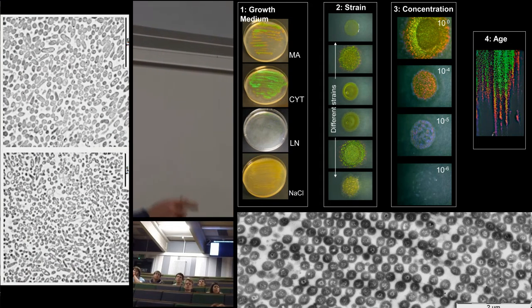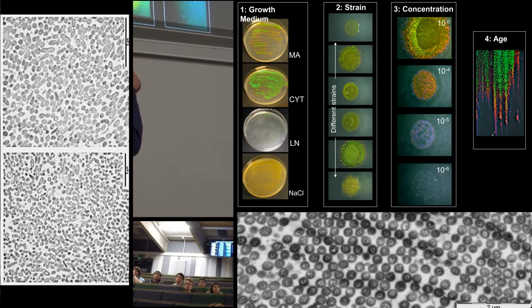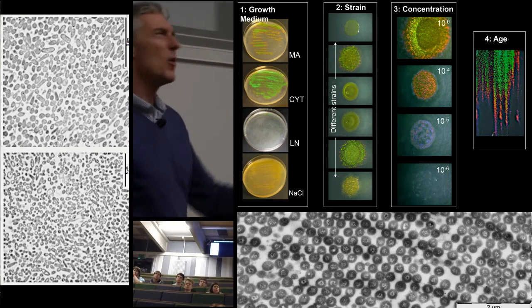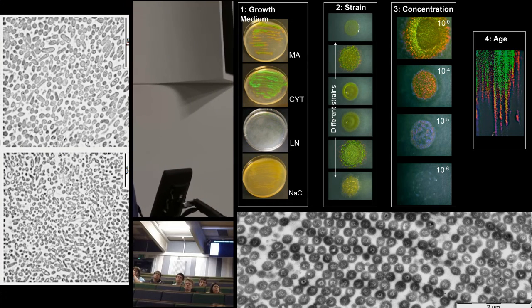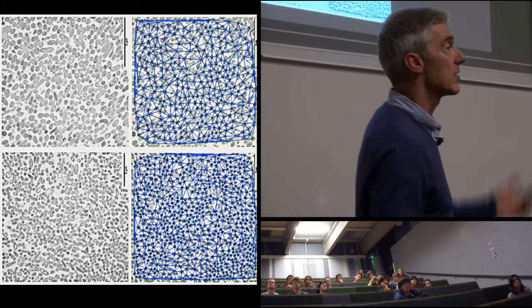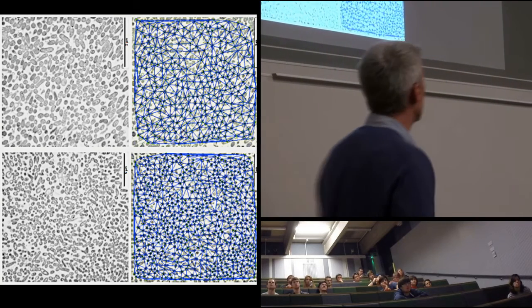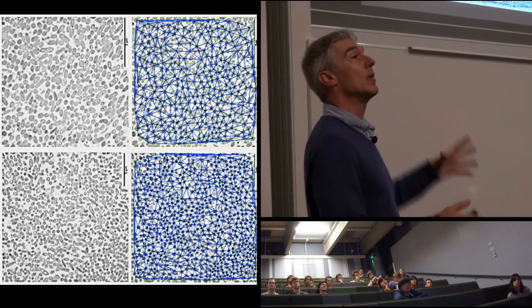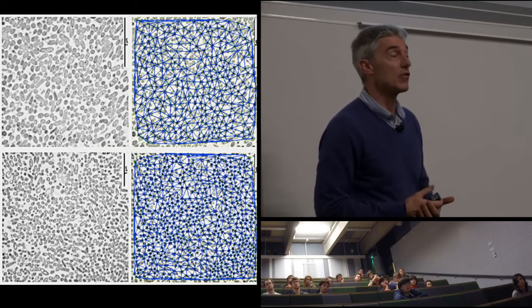Here are some TEMs of disordered bacterial films. Bacterial films that are like this or like that are not structurally coloured. And what do we notice? Well, we notice they're not very ordered. How do we quantify that? Well, you put a grid down. There's the grid, 2 grids. And then you use ImageJ or some software, you use the information that applying the grid provides you. In other words, it will tell you how big the centres are and how far apart they are if you use the right recognition software.